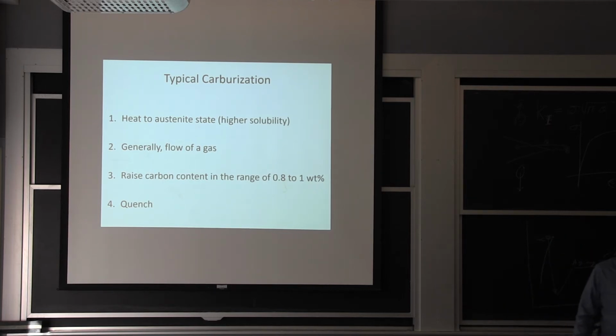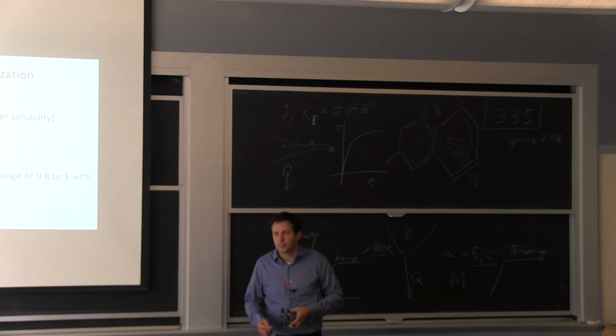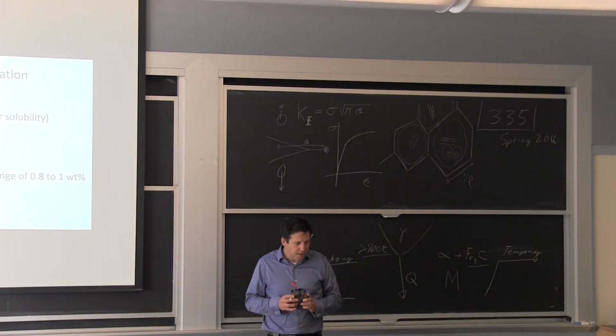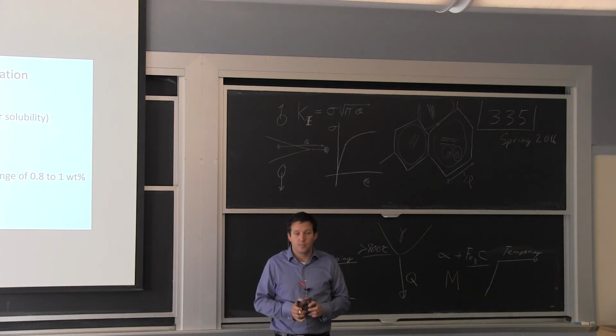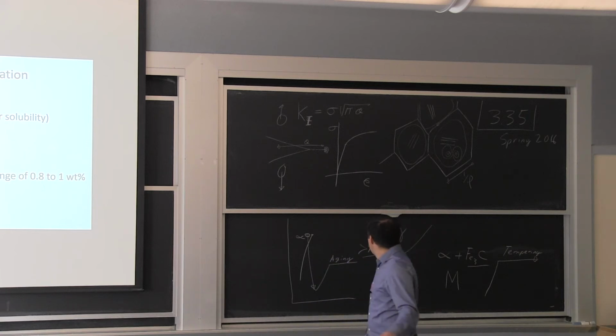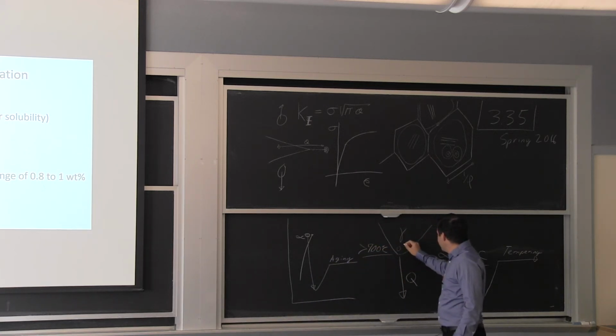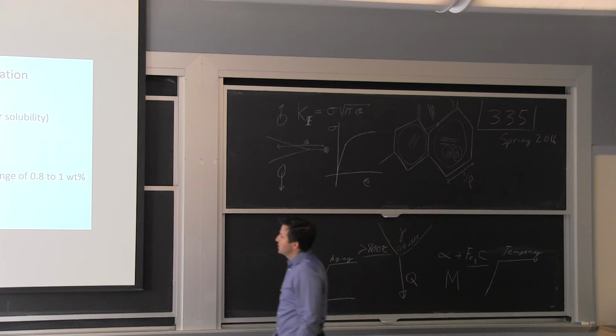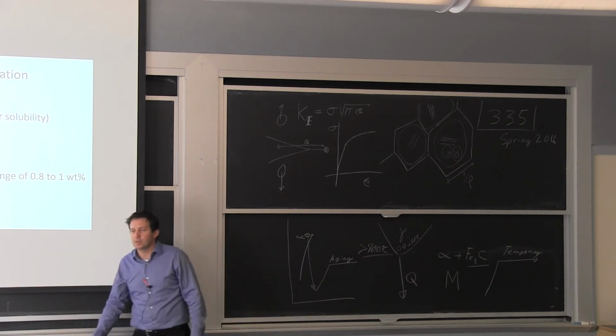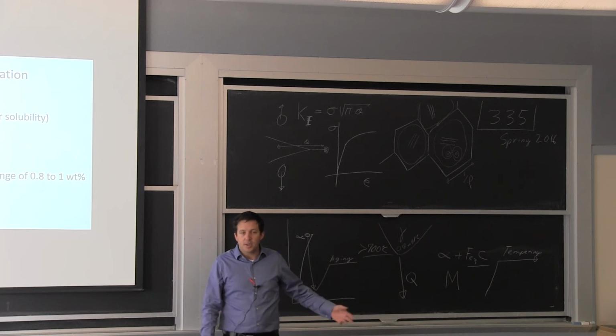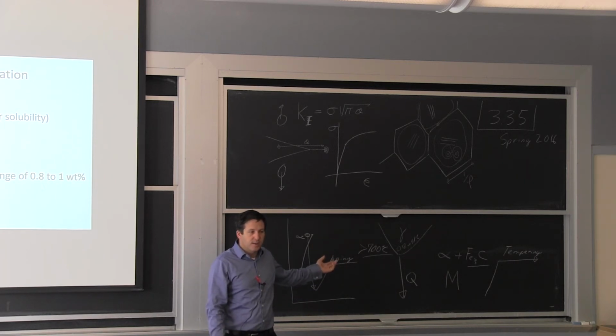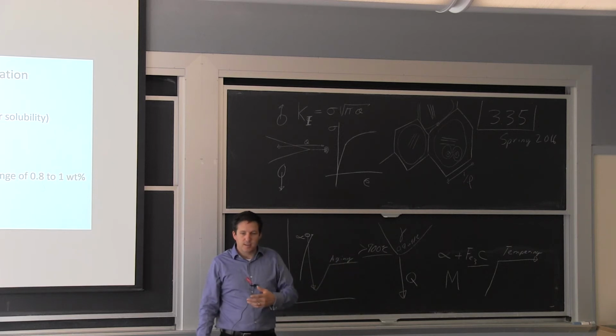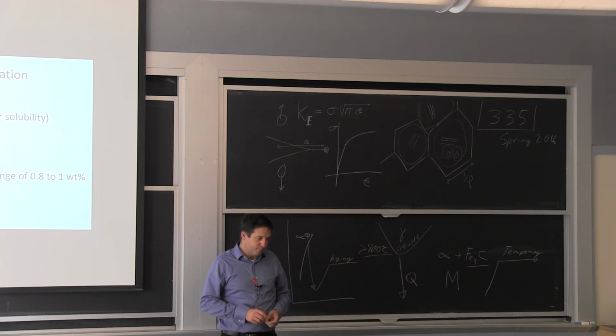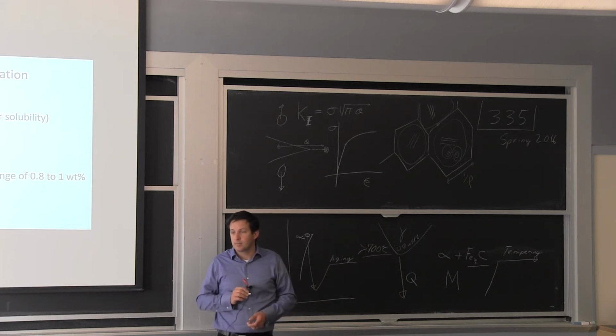So at high temperature, there's plenty of room for carbon in this structure. And you try to get close to the eutectoid concentration, if not even a little more. So you put quite a bit of carbon into your microstructure. If you remember, this location here was 0.8 weight percent carbon. And you put somewhere between 0.8 and 1% typically on the surface. And you do this relatively rapidly because it's not a super long or expensive process. You heat it up. You have a gas containing a lot of carbon, and you cool it down quickly.